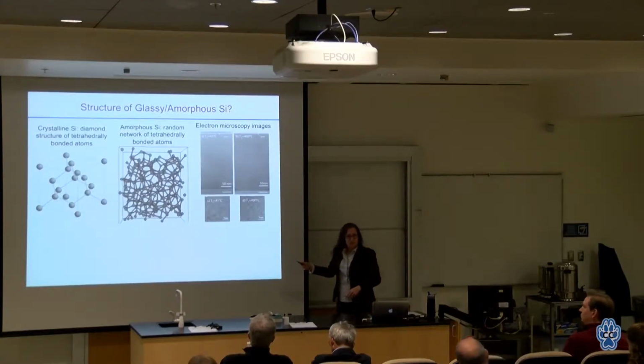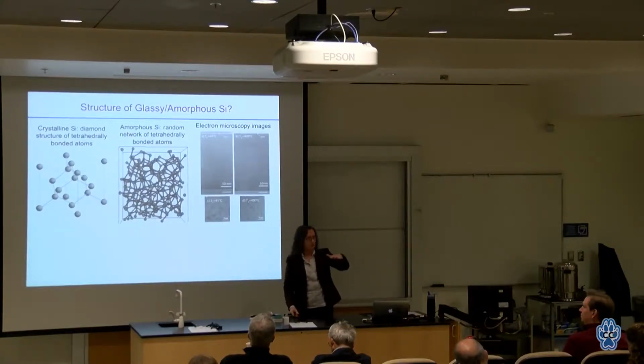When I do that, they land on a substrate. And as you can imagine, from the analogy of putting a cover slide above a pot of water, the temperature of that substrate matters. So the temperature at which I grow the film, not the temperature of the silicon. The silicon is glowing orange, hot, molten. But the temperature of the substrate that I'm using to grow the film, that's going to matter.